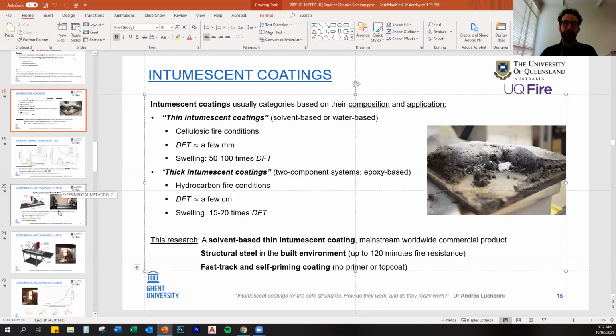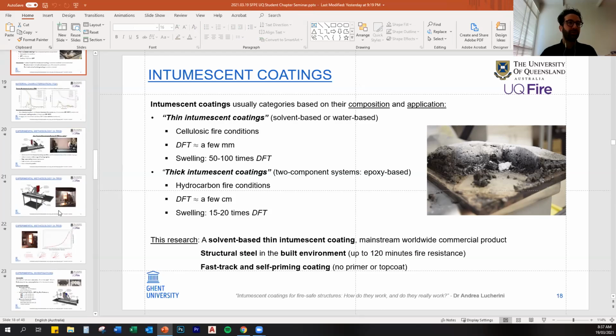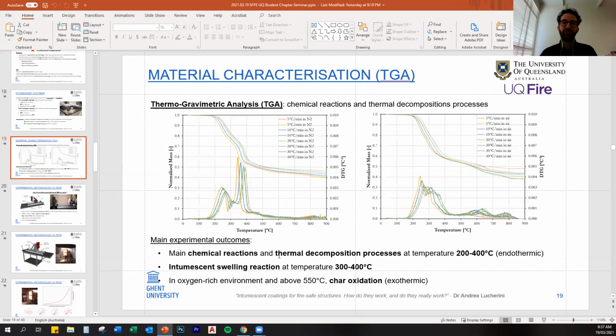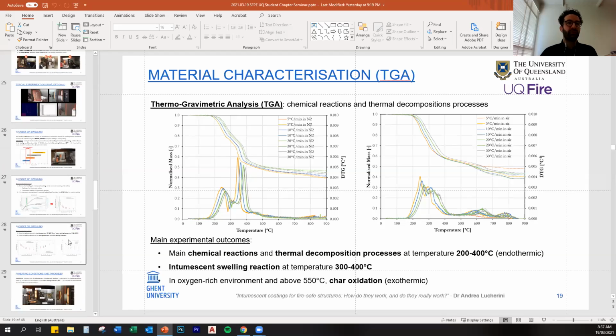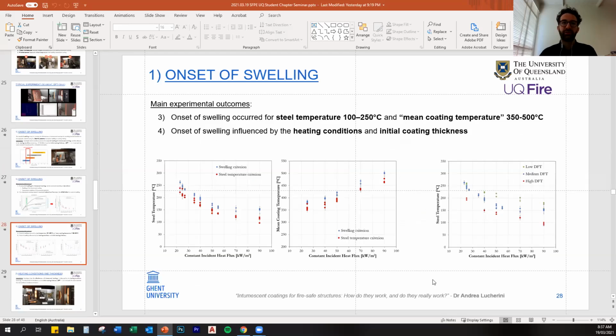And regarding the temperature of the swelling of the coating, I show you here in the TGA, you can have an understanding on the material level. So this coating would swell, in the case of a nitrogen atmosphere, between 300 and 400 degrees. The whole process would happen between 200 and 400 degrees. But I also show you when we go more to a heat transfer condition, when I have my plate exposed to an incident flux and has a thermal gradient within its thickness, you can see that I have a range of temperature based on the incident flux. If I look, for example, at the steel temperature, my swelling happened between 100 and 250 degrees. I hope I answered the question.